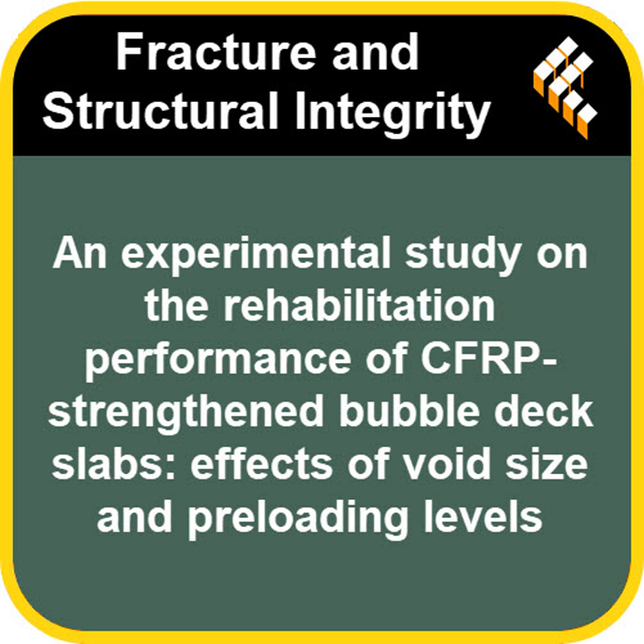Starting with the baseline. How did the unreinforced bubble slabs, the ones without CFRP, compare to the solid concrete control slab? Yeah, this is where we start to see that inherent trade-off pretty clearly. The unreinforced 50-millimeter void slab, which they labeled SB50, showed a 4.1% reduction in its ultimate load capacity compared to the solid slab. Only 4% down. That's not too bad. Not terrible, no. But interestingly, it had a 9.3% increase in deflection at that ultimate load. Ah, so it sagged noticeably more. Yes. Even though the load drop wasn't huge, the stiffness was affected. So right off the bat, we're seeing that weight reduction comes with a performance hit, especially in stiffness.